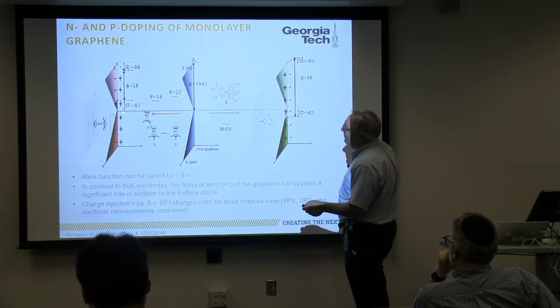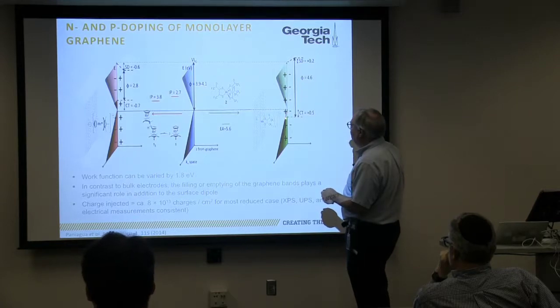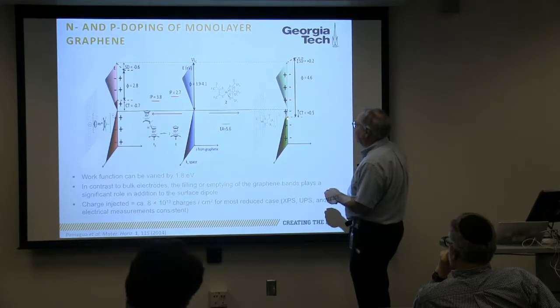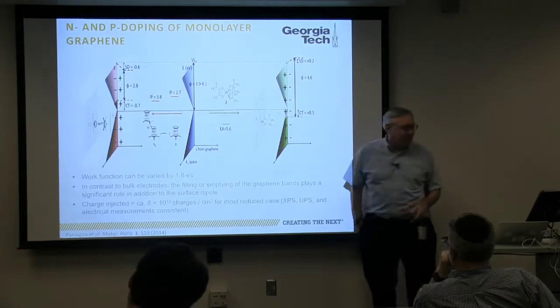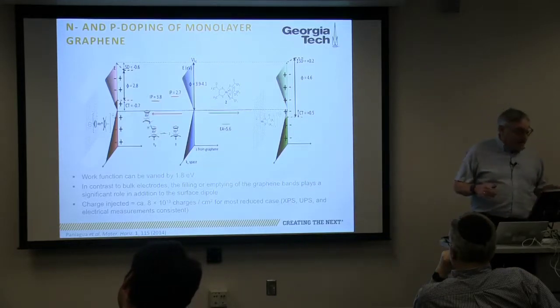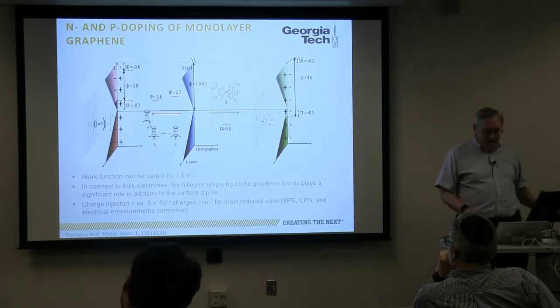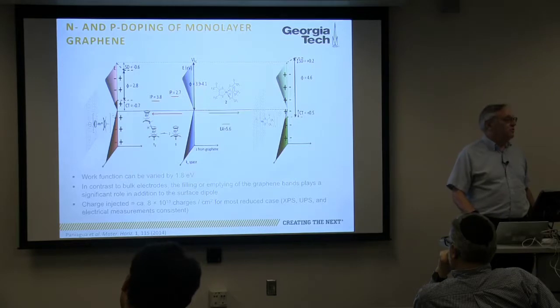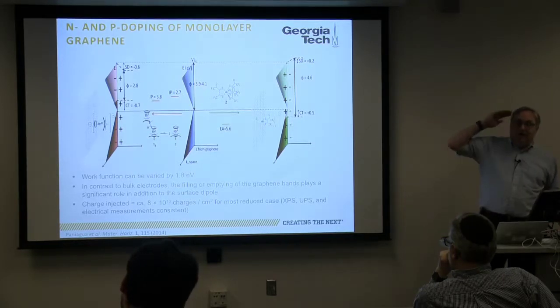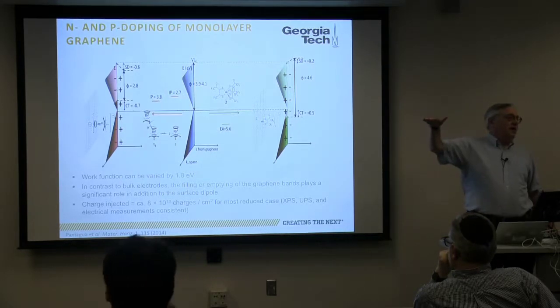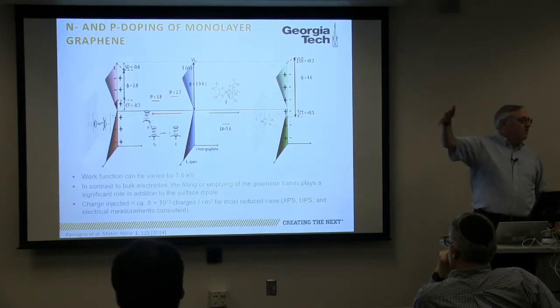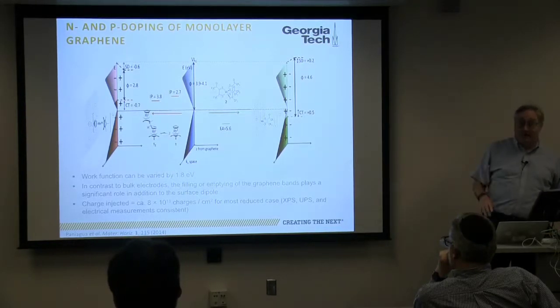When we n-dope graphene, we begin to fill the conduction band. When we p-dope, we deplete the valence band. And we can modify the work function of graphene by, I show here 1.8 volts, but we can now modify it by well over 2 volts. And we can convert graphene into a very good cathode for injecting electrons into materials, for example, for organic light-emitting diodes.